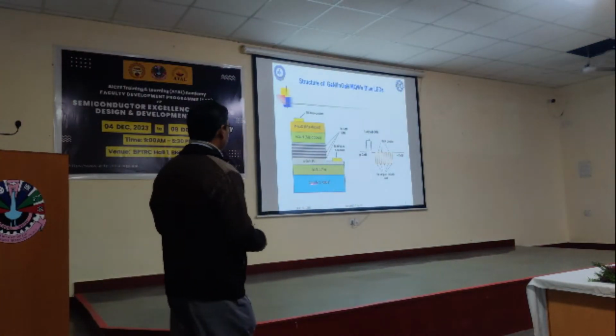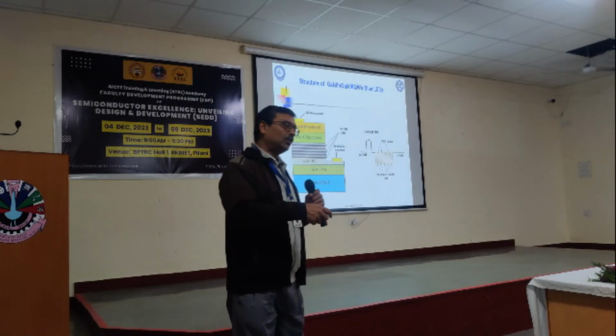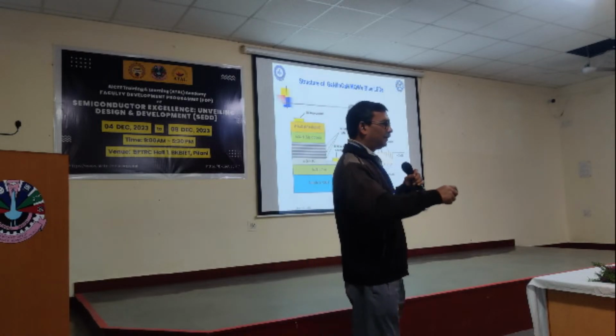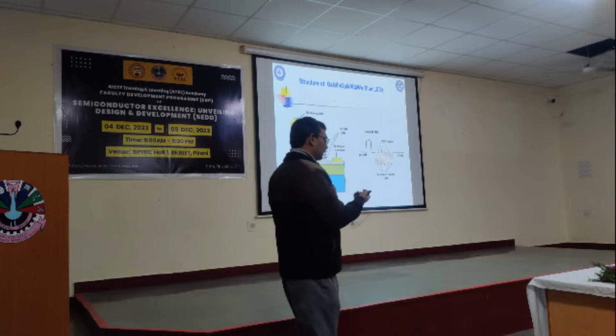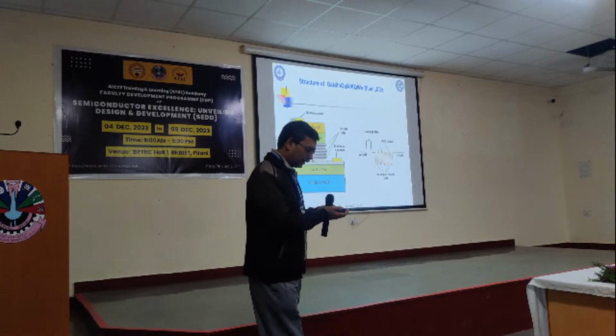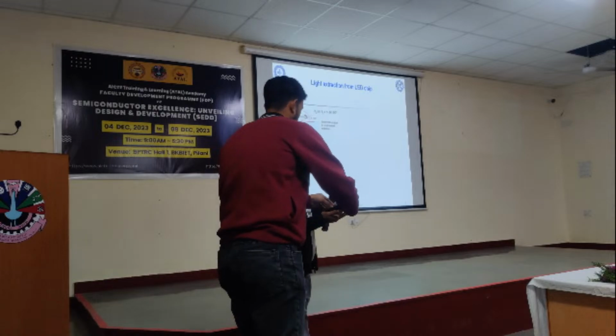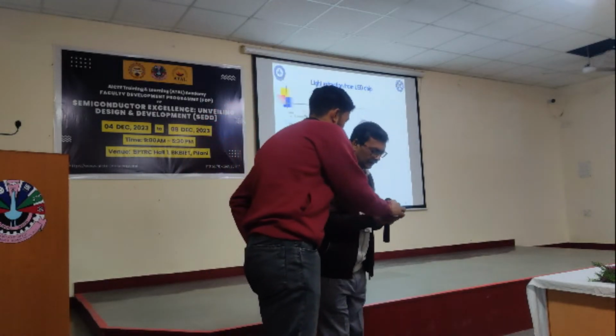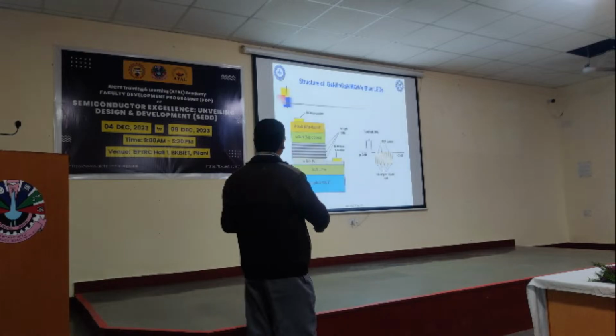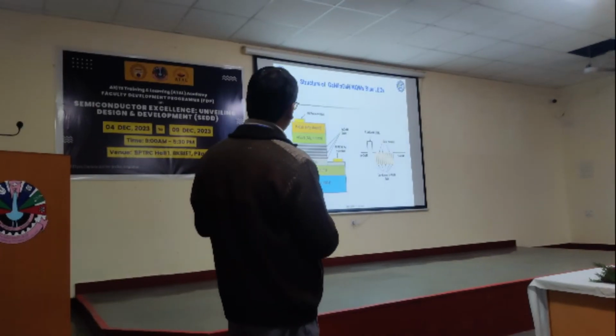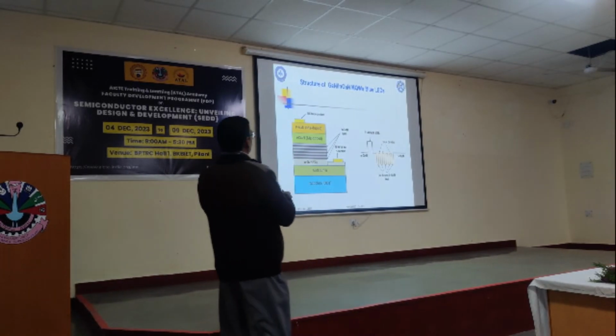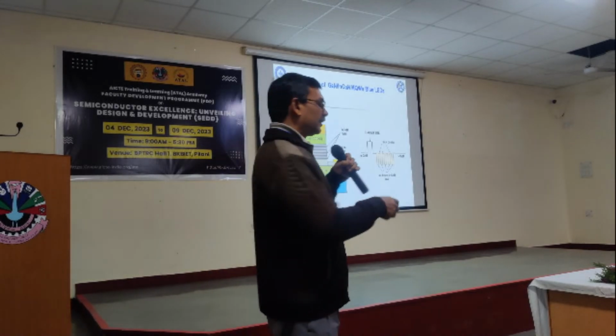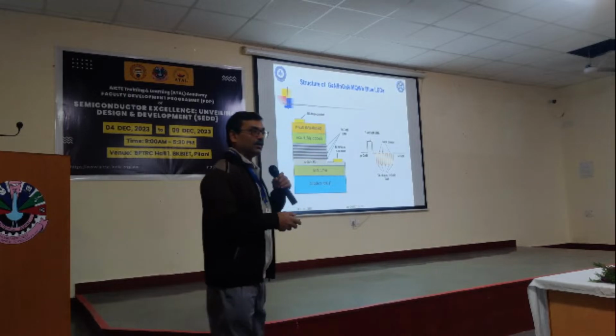The lattice constant of sapphire does not match with gallium nitride. So we have to go for a certain buffer material, and this buffer is mainly for making the interface area in between gallium nitride and sapphire for matching the lattice constant.